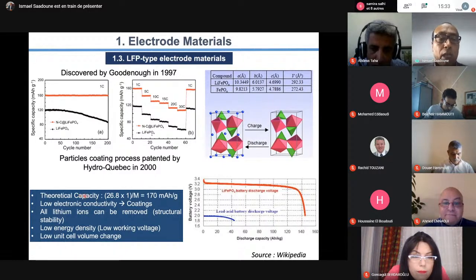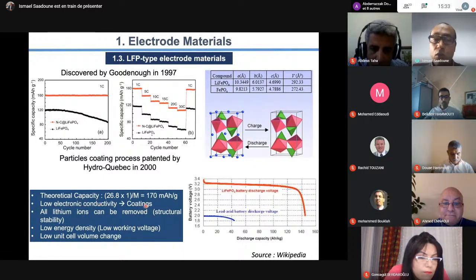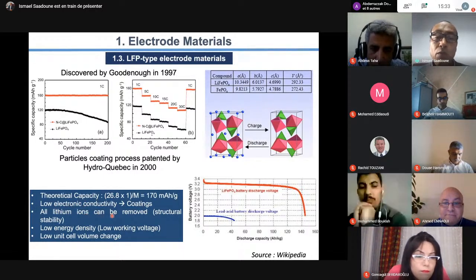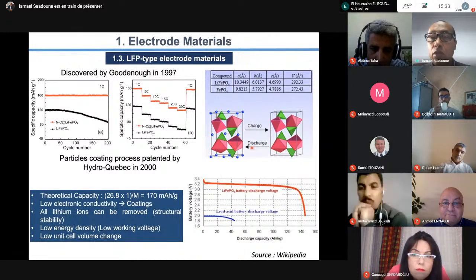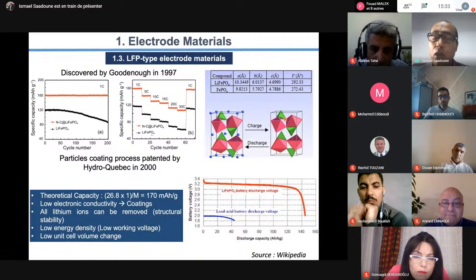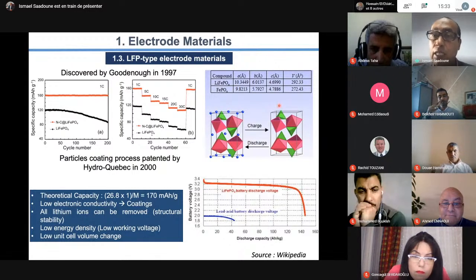So the theoretical capacity is 170, but it has low electron conductivity, so we need to coat it. And all the lithium ion can be removed - you see here is the starting material, and we can remove all the lithium, so we have a bigger capacity. In the oxide, for example, we can remove only 50% of lithium. In the case of iron phosphate, we can remove all the lithium because the structure of phosphate is stable.